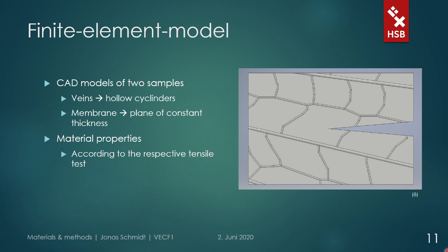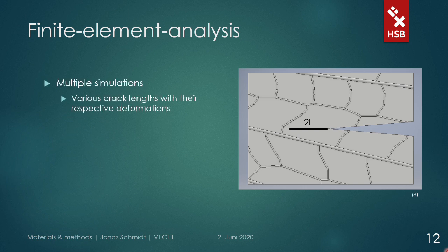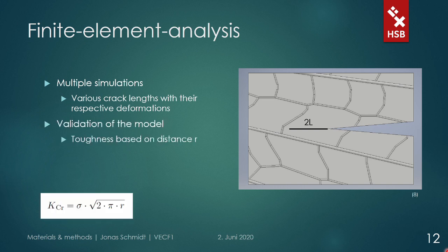For each sample, multiple analyses were conducted where the crack length was slightly altered from simulation to simulation and the respective displacement that led to that crack length was applied. In that way, the crack propagation of the actual tensile test was simulated in simple linear elastic and static observations. Before the TCD was applied, the finite element model was validated by calculating the fracture toughness based on the resulting FE stresses, yielding a fracture toughness-distance relationship starting from the crack tip, which could be compared to actual toughness values from the tensile test.